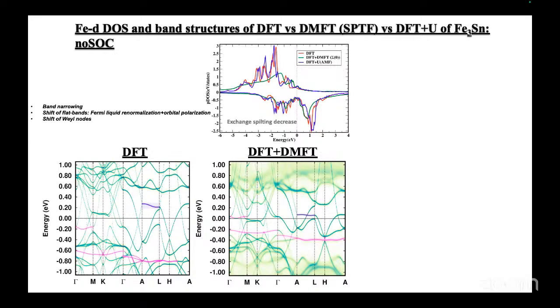With respect to the Weyl nodes, we see that the Weyl nodes which were there in the DFT have shifted a little down, and also changed position with respect to the high symmetry points. To further analyze that, we expect in DFT plus DMFT the Fermi liquid renormalization and the orbital polarization, and to investigate this combined.